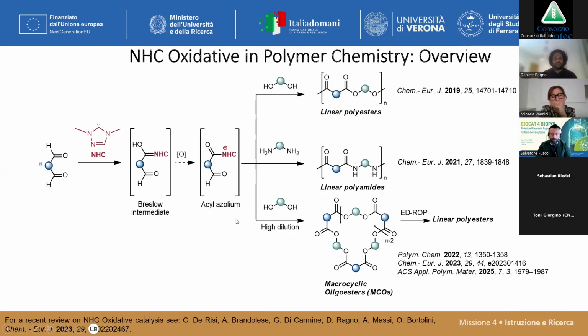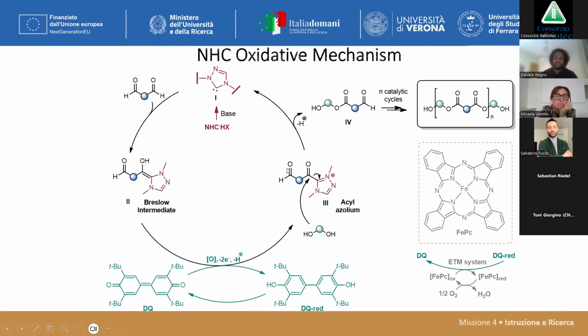And what's very funny and unique about this methodology was that if we consider the common strategies for step growth polymerization, we can use, of course, a diol, a diamine, working with polyesters, polyamides, but this reactant here is quite uncommon because normally you use very activated substrates: diesters, diacyl chlorides, dianhydrides. Well, in this case, we were able to use dialdehydes. And we were able to synthesize a lot of polymers using some bio-based monomers, especially taken from the lignocellulosic matrix, so 5-HMF derivatives.